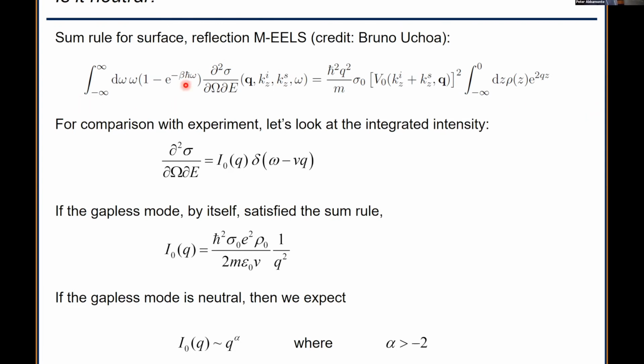So this is the doubly differential scattering cross section. This is a Bose factor, so you have to put in the temperature. These are the matrix elements, which you can write down. They're just Coulomb matrix elements. And this is not the electron density, but the surface electron density. So rho of Z is a measure of how the electron density falls to zero as you go from the material into the vacuum. And for small momenta, this is basically a step function. So this whole thing you can simply calculate by hand on a piece of paper.